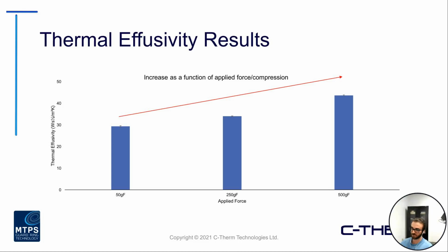In reality, if you were to sample many more pressure points across a wider range, you will start to run into areas of diminishing return, where maybe at the low end you see very little effect. As you increase that force load, it starts to dominate the measurement, and then maybe at the upper end, again, you hit that point of diminishing return where the sample is just really approaching a fully compressed state. But this will really vary depending on the type of sample, obviously the density of the material, the composition, in textiles and fabrics, even the weave and the pattern, the structure that is used. These will all have an influence on how they measure with respect to thermal effusivity and how those measurements will change as a function of, in this case, force.